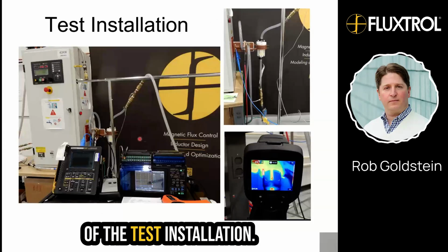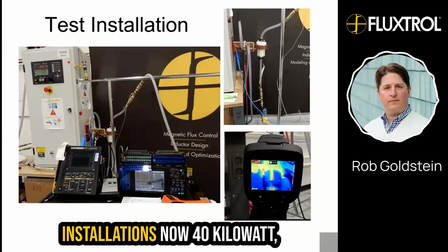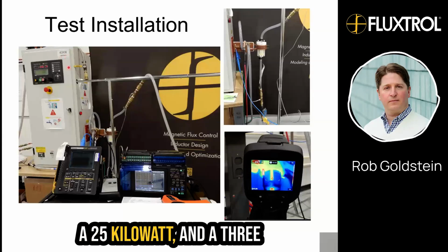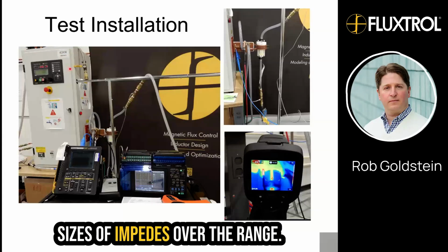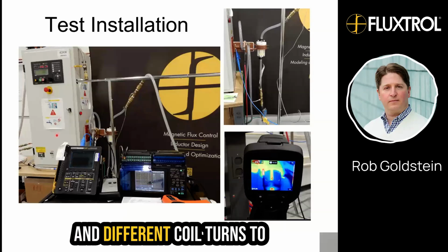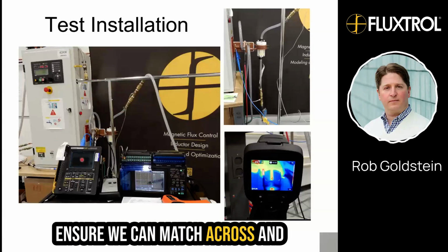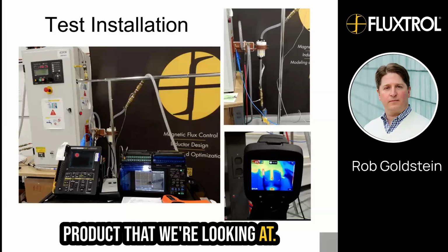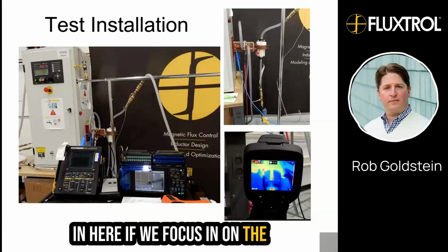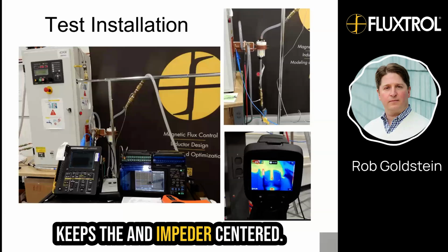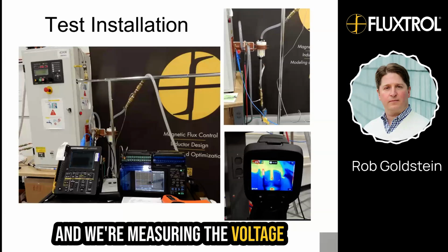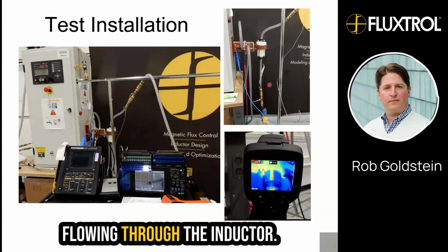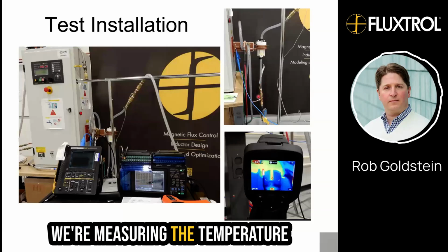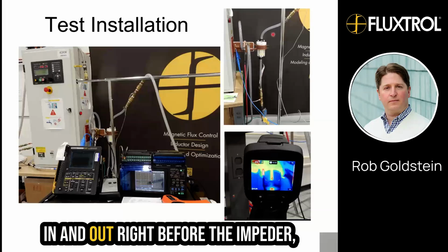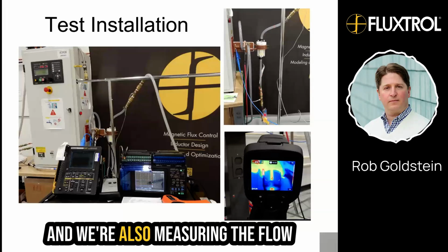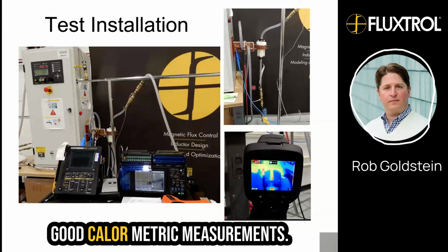Here's a couple pictures of the test installation. We've actually got 3 of these installations now: a 40 kilowatt, a 25 kilowatt, and a 3 kilowatt for testing different sizes of impeders over the range we're looking at, and different coil turns to ensure we can match across and test across the whole range of product that we're looking at. In here, if we focus in on the coil, we now have a holder that keeps the impeders centered, and we're measuring the voltage on the outputs, and we're also measuring the current that's flowing through the inductor. We're measuring the temperature in and out right before the impeder, and we're also measuring the flow to the impeder, so we can make good calorimetric measurements.